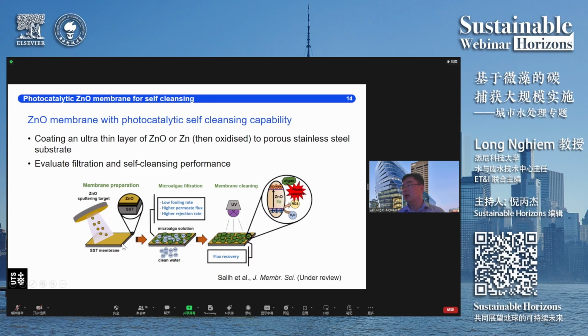Actually, we have two techniques to develop the zinc oxide on the membrane surface. Technique number one, we deposit zinc oxide directly onto the membrane surface. And technique number two, we first deposit zinc metal on the membrane surface, and then we oxidize at 800 degrees centigrade to convert zinc metal into zinc oxide. So we also end up with zinc oxide on the membrane surface.